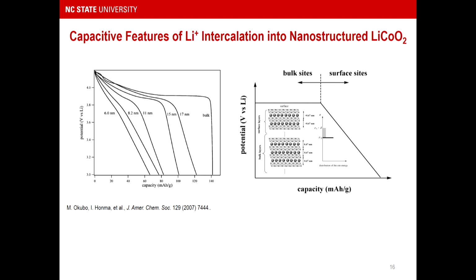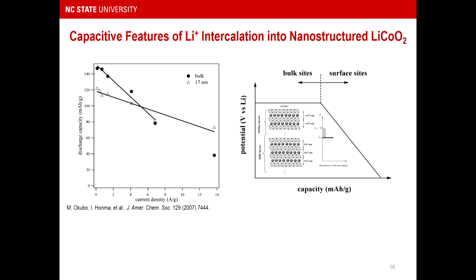And so something like lithium cobalt oxide that shows a galvanostatic discharge curve that looks something like this, as you make it smaller and smaller in dimensions, begins to look more and more like you have a very strong dependence of the potential on the extent of the state of charge. So you could essentially call that capacitive, but we know it's linked to cobalt redox, pseudocapacitive, if you will, mechanism. And what's important about this is that now you have materials that are storing ions not just at the surfaces, but actually near the surface or somewhat in the bulk, and providing very, very high current densities as a result.